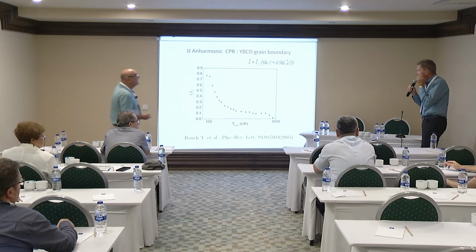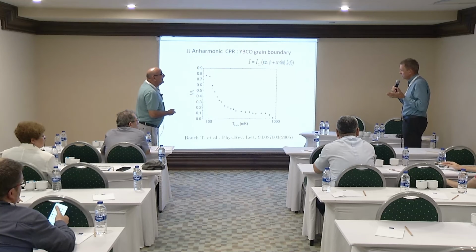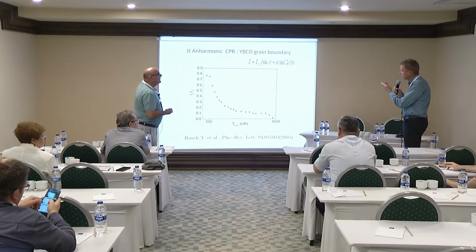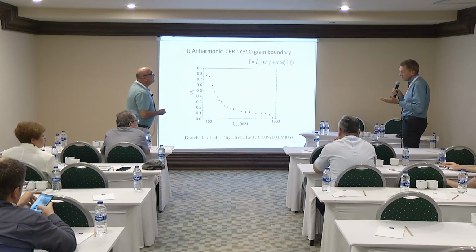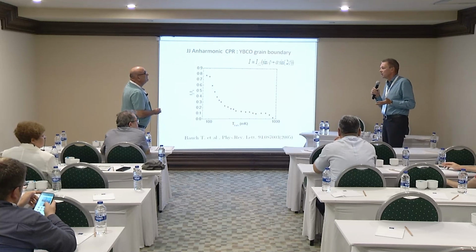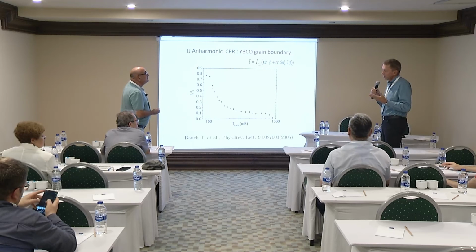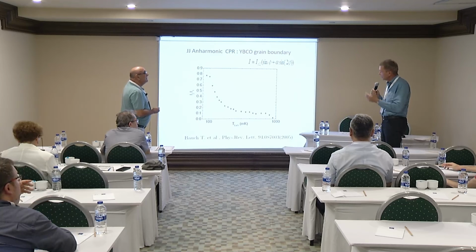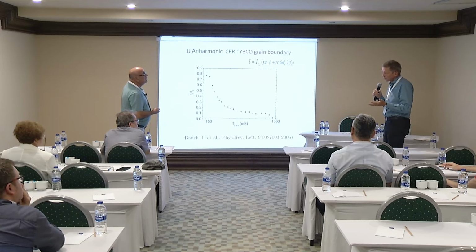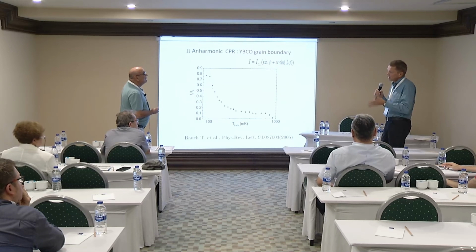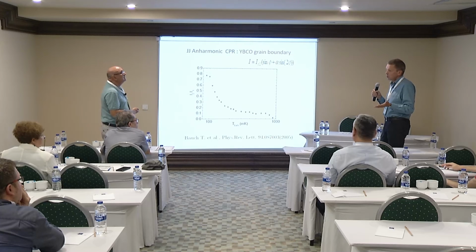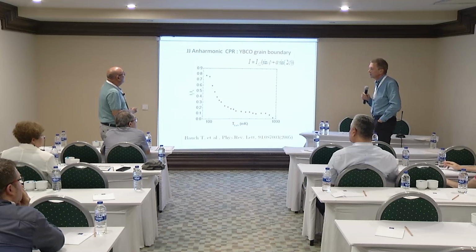I would have a question: what kind of materials do you consider? Because so far there are no qubits made of high-Tc YBCO junctions. The reason is that they have very high loss, and qubits require small dissipation. Once you take exotic materials like this, or two-band superconductors, the losses are much larger than in conventional tunnel junctions, and the qubits don't work. So I wonder which particular materials, except for YBCO, did you consider here?